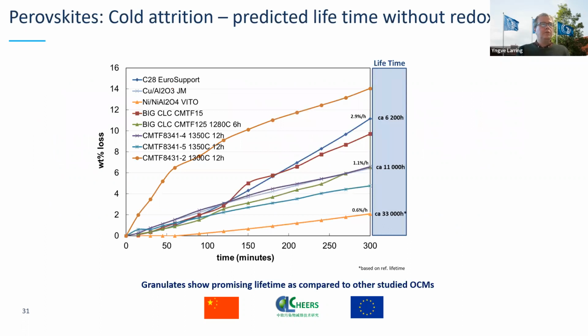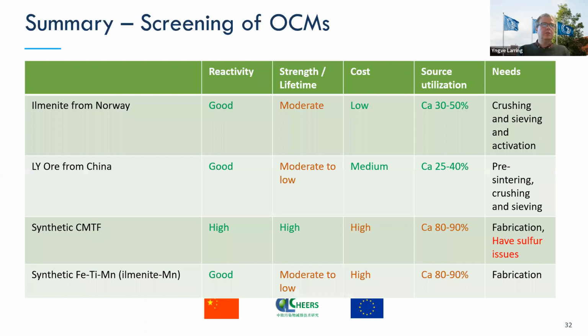We did some cold attrition of this material as well, and we see that they are equal to other good materials like nickel and copper. A little bit not fully so good as the nickel aluminate, but they are in this same range as a lot of other material tested before, meaning that they have a good strength. The one which has the lowest strength is the one with a little bit too low sintering temperature, making it a little bit less strong. So this is important to optimize.